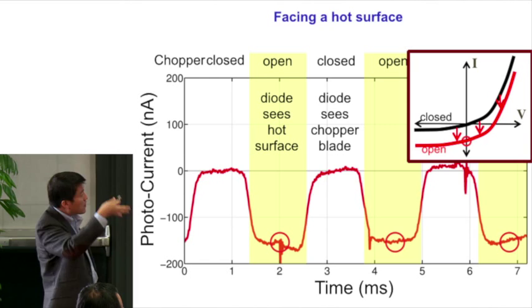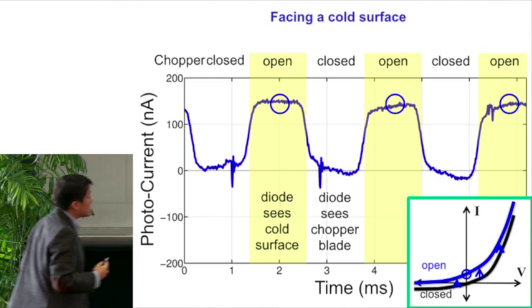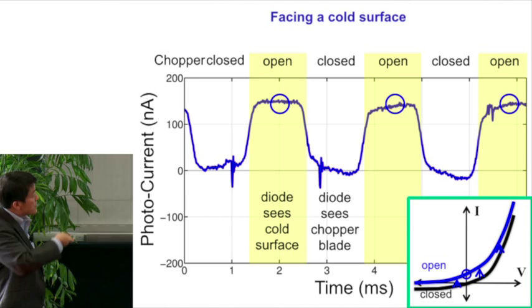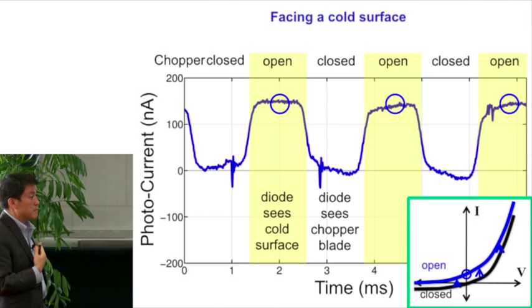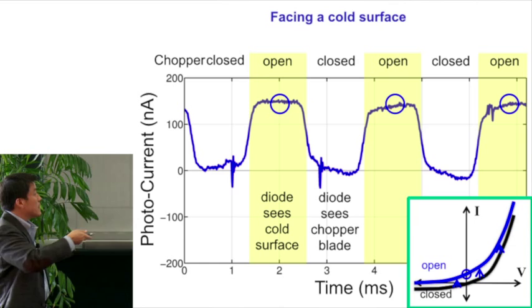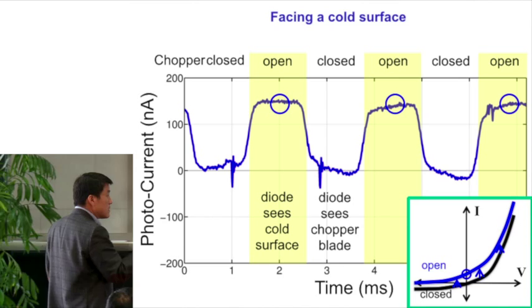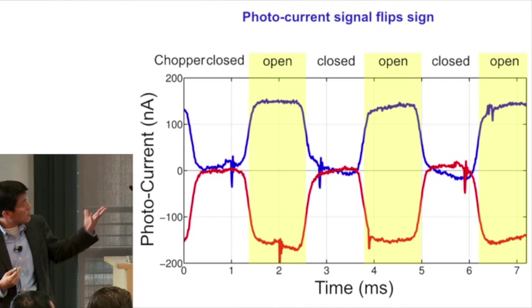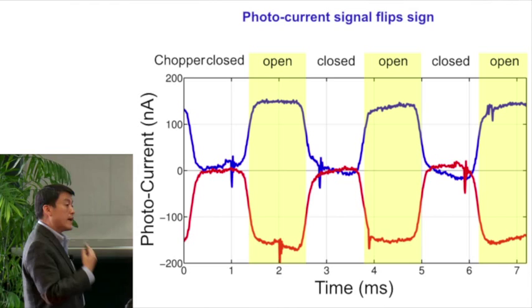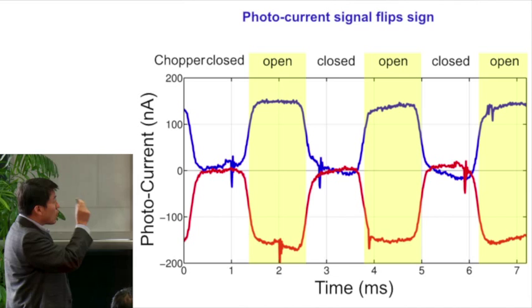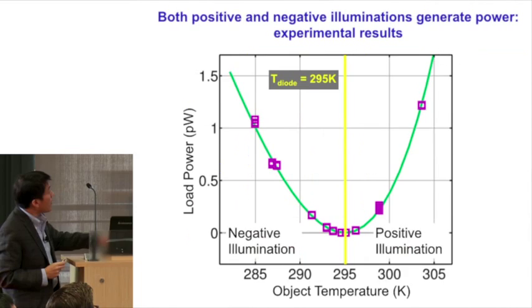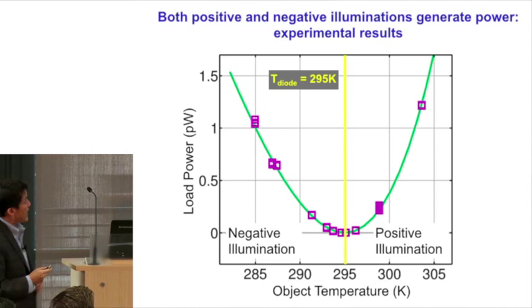On the other hand, if you face a cold surface, the curve actually flips. In this case, again, when the chopper is closed so that the diode does not see the emissive surface, you don't have any current. And when the diode sees the emissive surface, you now have a positive current. And that's consistent with the shift of this curve into the second quadrant. So in fact, if you were to compare these two curves, you would see a very distinctive 180-degree phase shift with respect to the chopper position when you look at the current as a function of time. And in both cases, therefore, the diode can actually extract power.